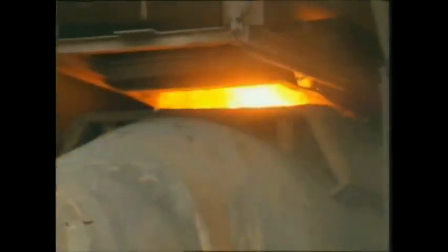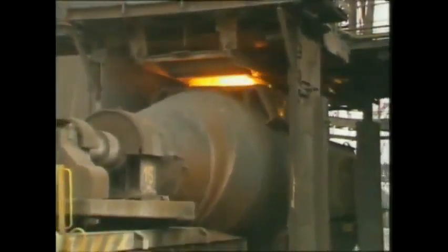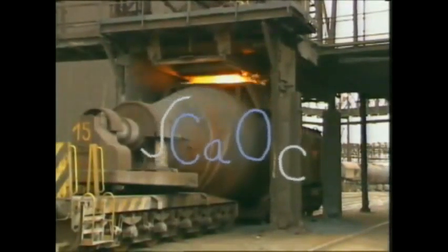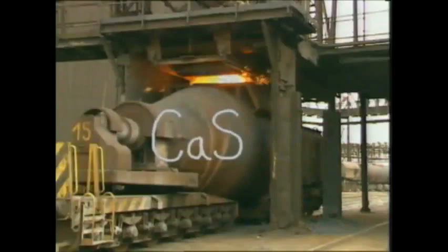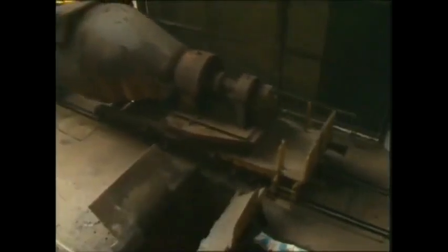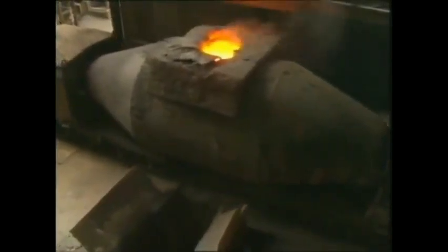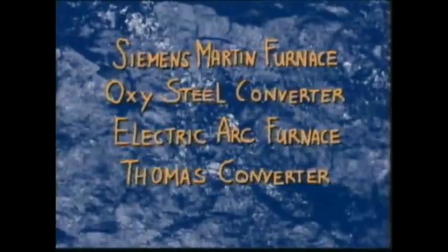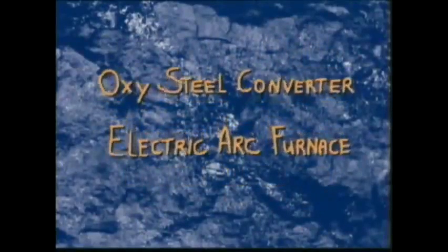It's here that the real steelmaking process starts, beginning with a desulfurization process by injecting lime powder. To avoid loss of ductility at high temperature, a sulfur reduction to values lower than 0.010% is necessary. Now the liquid pig iron is transported to the steel plant. Steelmaking can be carried out in several processes. Nowadays, only the oxygen steel and electric arc processes are relevant.